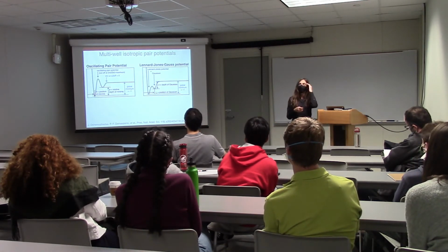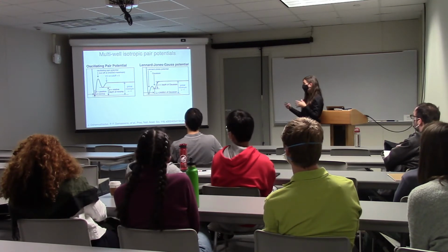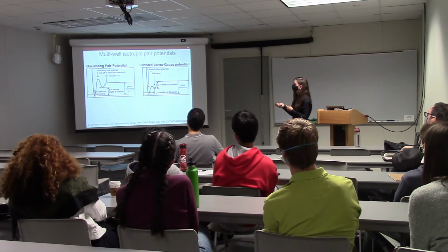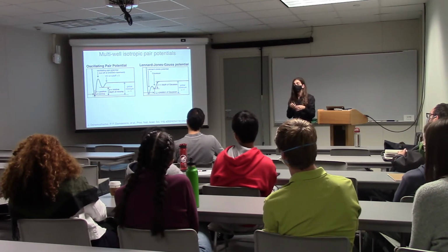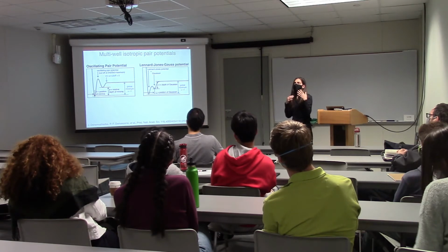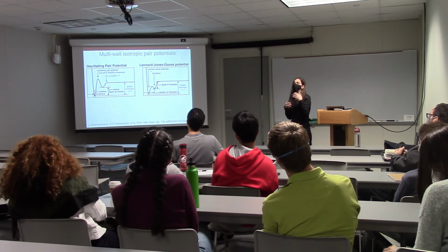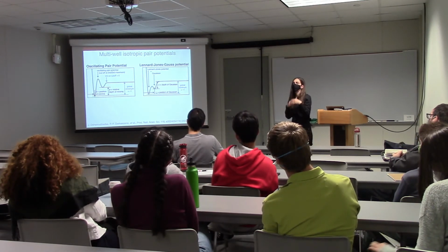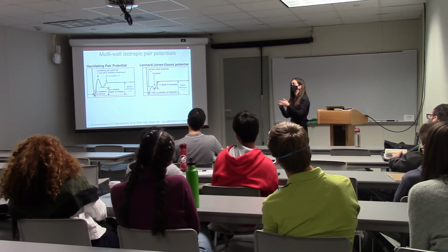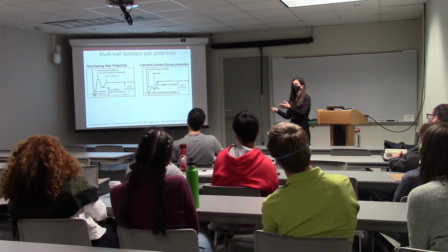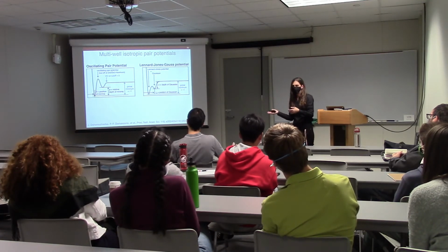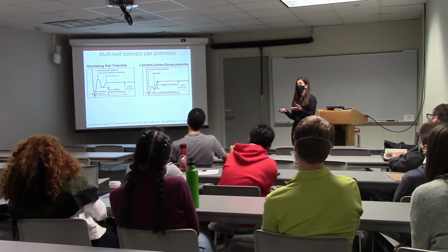So these are the interaction potentials with which our particles interact now. They look kind of made up, but actually the oscillating pair potential is used relatively frequently in dynamics studies of metals. People often measure mechanical properties like this. They use empirically fitted potentials to say, okay, this mimics the aluminum, copper, or whatever interaction, and they're using this as the functional form of their interactions for hard matter systems.